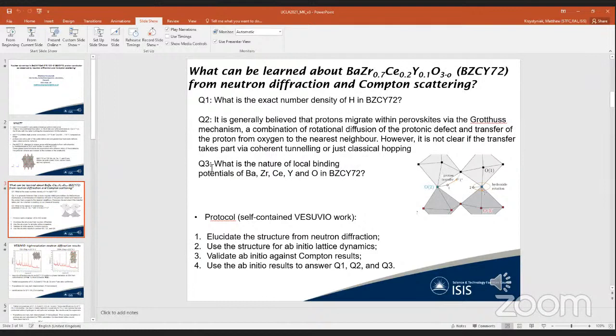Because it is believed to be a Grotthuss mechanism, a combination of rotational diffusion of protonic defect and transfer of the proton from oxygen to the nearest neighbor. It is known from spectroscopy that hydrogen bond is formed, but we don't know whether the mechanism of proton transfer is a classical one, a hopping, or is it a quantum one, whereby you have a coherent superposition of the proton wave function and then basically a proton tunneling mechanism.